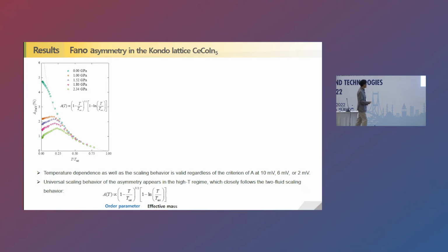And with decreasing temperature, you can see that the deviation from the ambient pressure data increases. The dotted line is based on the so-called two-fluid model, which consists of two terms. One is the increase of effective mass, and the other is the so-called order parameter of the fraction of Kondo liquid. You can see that it nicely captures the evolution of the asymmetry as a function of temperature.